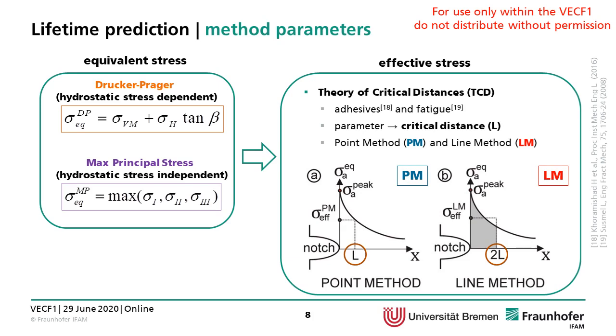It has been shown valid for adhesives and fatigue in many applications, and is based on a parameter, the critical distance. And here we use both approaches, the point method and the line method. The point method, given the stress distribution, you take the value of the effective stress at a distance of half the critical distance, and using the line method, we take the effective stress as the integration of the stress for 2 times the critical distance.